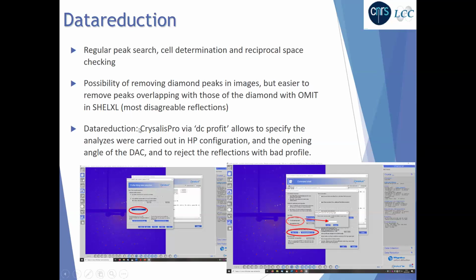When performing the data reduction in CrysAlis using DC Profit, we specify that the analysis was carried out in HP configuration. And so we can indicate here the opening angle of the DAC, and it is recommended to reject the reflections with bad profile.